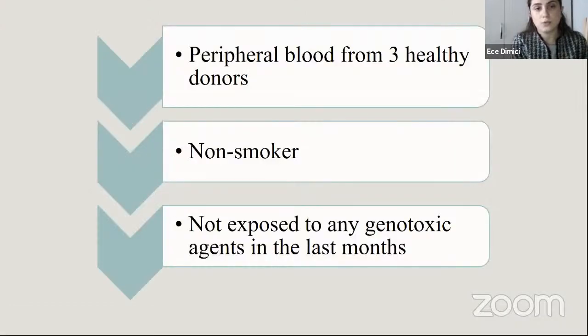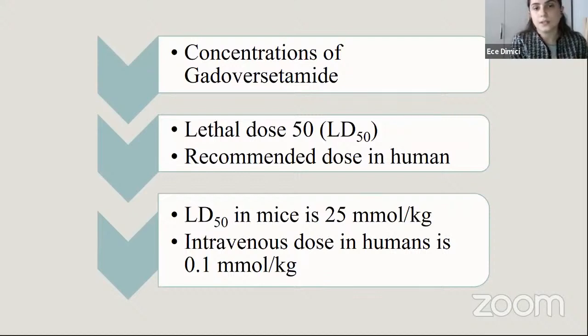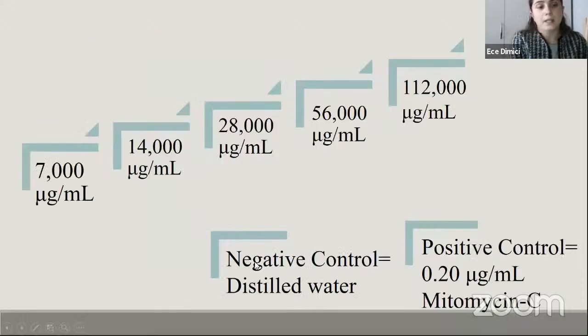If we look at the materials and methods, firstly, peripheral blood from 3 donors was obtained, who were non-smokers and not exposed to any genotoxic agents in the last months. The concentrations of gadoversetamide were chosen according to its lethal dose and recommended dose in humans. Its lethal dose in mice was 25 millimole per kilogram, and its intravenous dose in humans is 0.1 millimole per kilogram. So the concentrations selected started from 7,000 microgram per milliliter to 112,000 microgram per milliliter. Distilled water was used as negative control, and the positive control was mitomycin C.